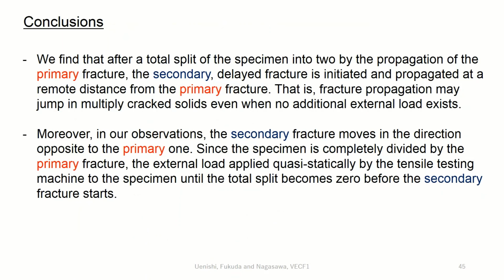Here are our conclusions of the observations. We find that after a total split of the specimen into 2 by the propagation of the primary fracture, the secondary, delayed fracture is initiated and propagated at a remote distance from the primary fracture. That is, fracture propagation may jump in solids with multiple cracks even when no additional external load exists. Moreover, in our observations, the secondary fracture moves in the direction opposite to the primary one.